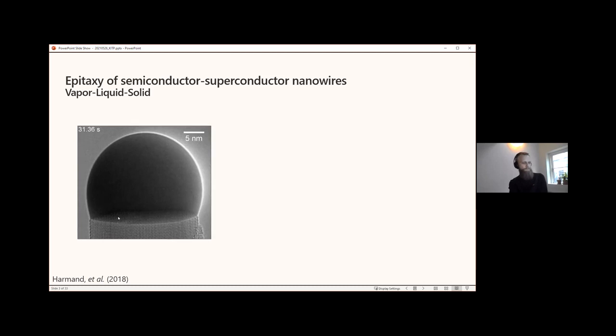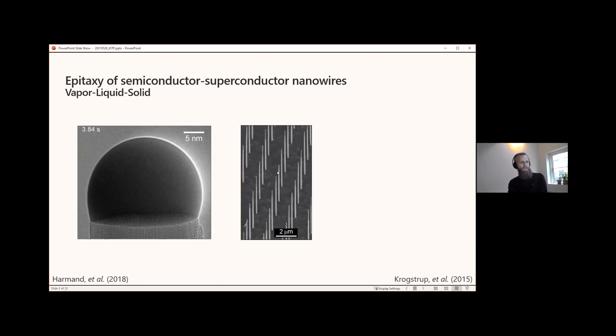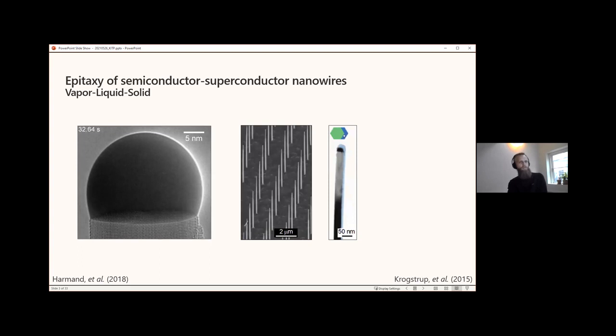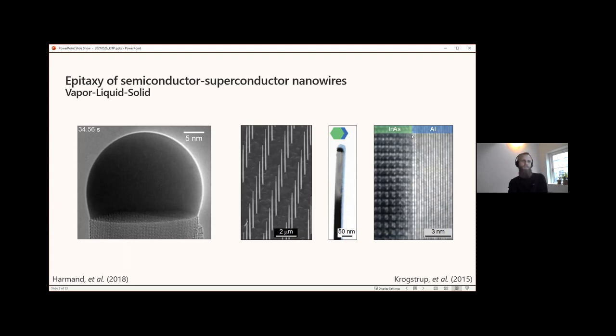So these wires are grown to a certain length, most of the time something like 10 micrometers, and then you can also deposit a superconductor, in our case it's aluminum, on either part of the wire or a full shell of the wire. In this talk, I'm going to be mostly talking about the partly coated wires. And the trick is to deposit this superconductor in situ without breaking the vacuum such that the indium arsenide, which is our semiconductor, indium arsenide interface remains pristine and oxide-free. And this is the epitaxial interface that we are dealing with.